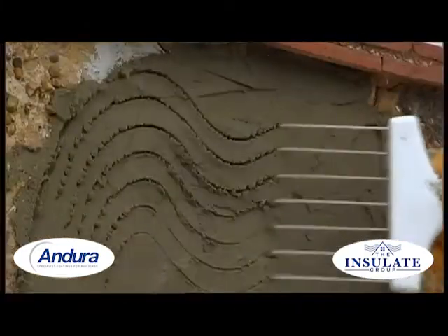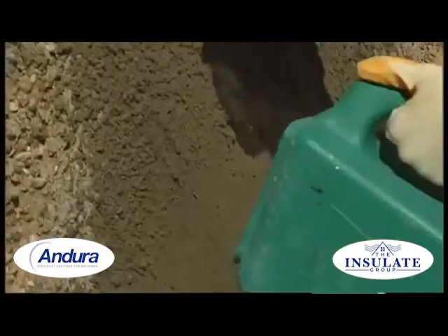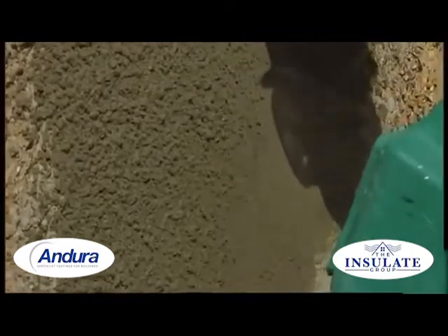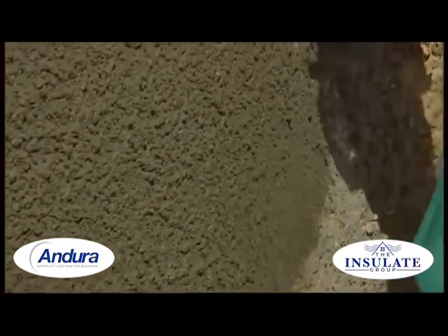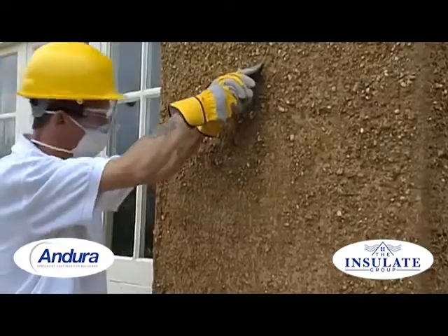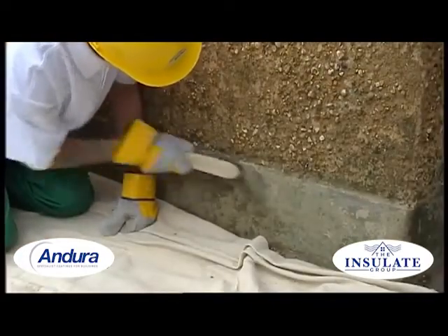Damaged areas of render or pebble dash are cut back and then treated with special bonding primers and restored with two layers of a sand-cement mixture. Pebble dash finishes are matched by spraying similar-sized aggregate onto the surface with what is known as a Tyrolean gun. Once the repairs are done, the cleaning down begins.